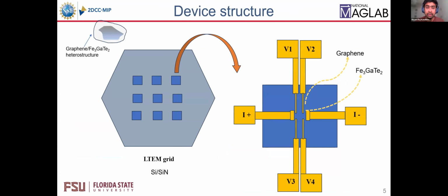It has 9 windows, which are the TEM windows. So if we transfer our material on top of these windows, we can do the TEM imaging. The windows are made up of silicon nitride, and the thickness of that membrane can vary from 15 nanometers to 50 nanometers.